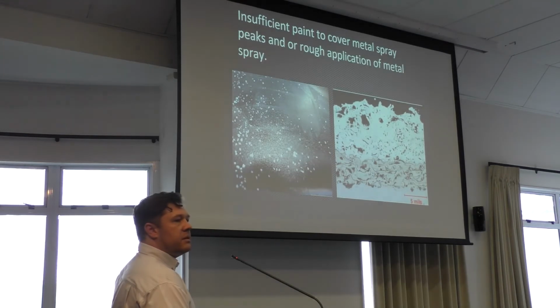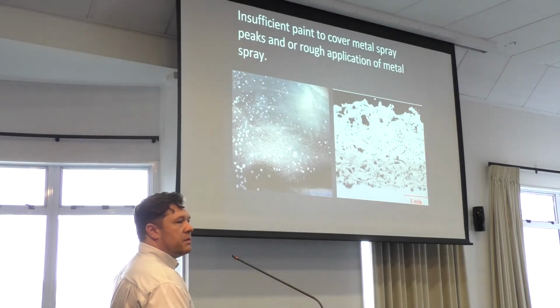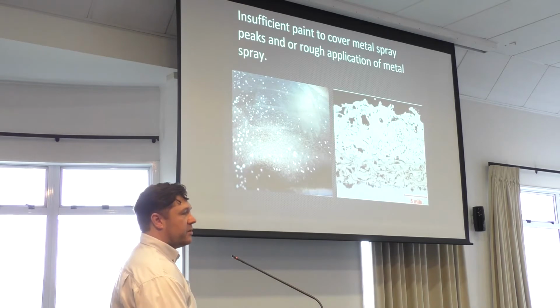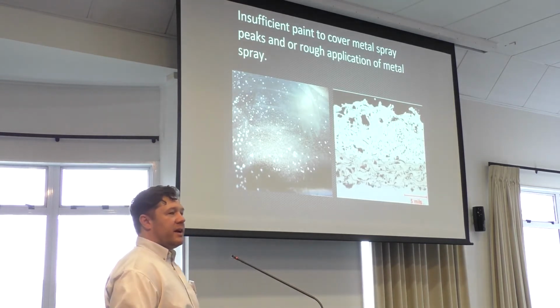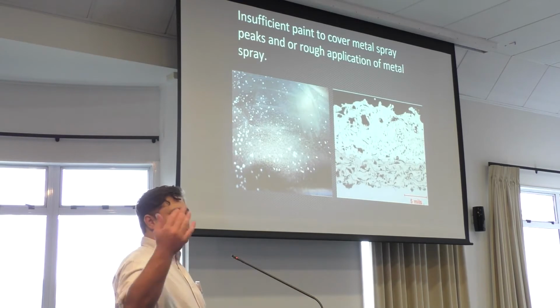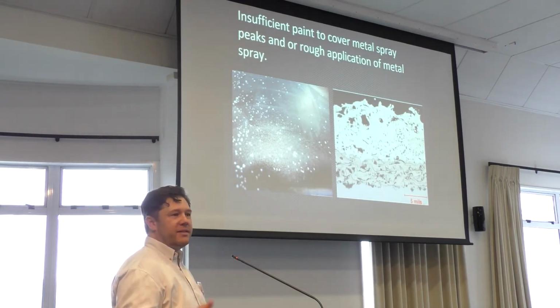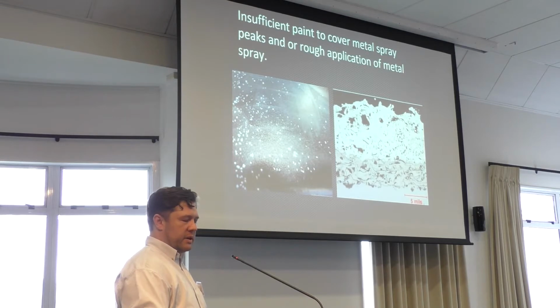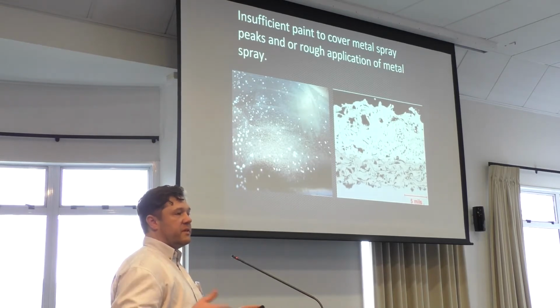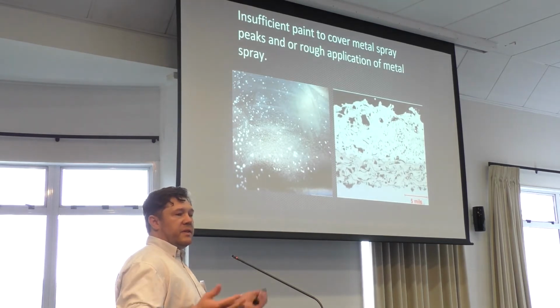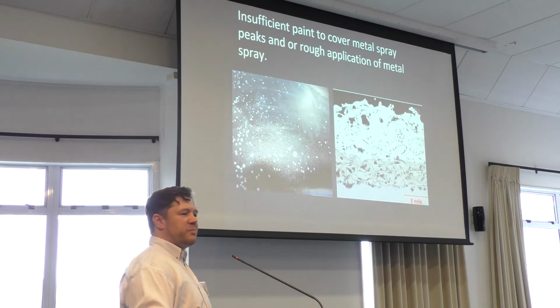Hey Matt, can you just talk a bit about that definition of a rogue peak? Like we get specs coming through all the time, and it's very interpretable. Okay, so the rogue peak, I can't really give you a definition of it. I mean, we can say that it's a peak that's larger than the average peak. I'd prefer to use a term like sanding the profile to a specific surface profile of say 50 or 75 microns. So if we were putting 75 microns of paint over it, obviously you need a surface profile that's pretty smooth so that you're getting a good continuous coating over the top of the peaks.